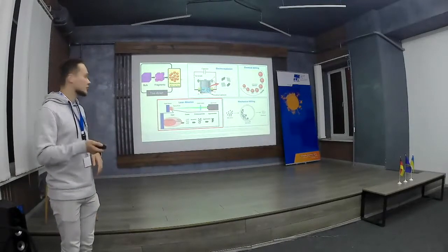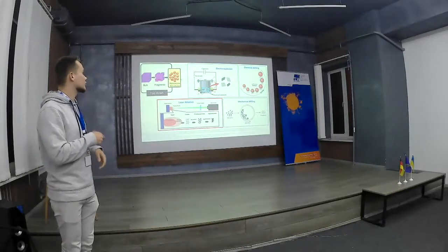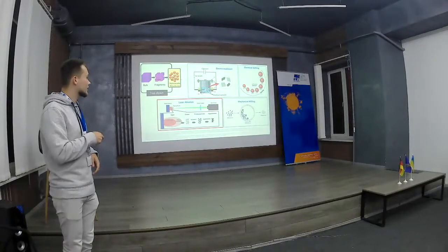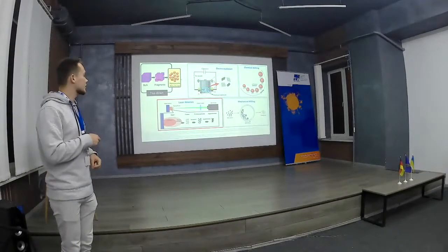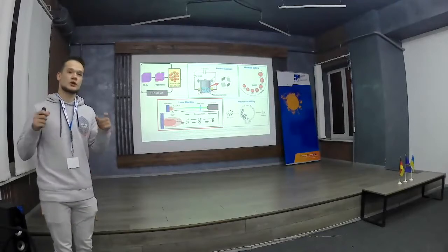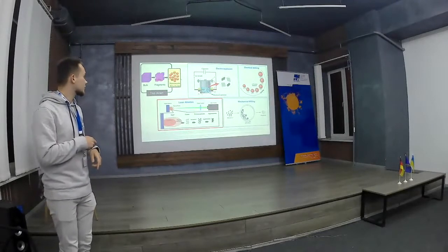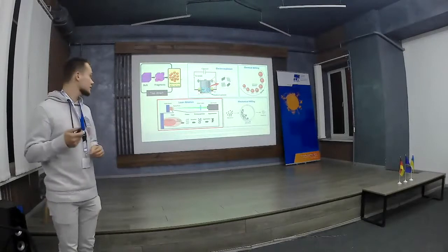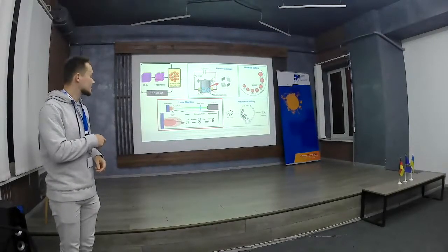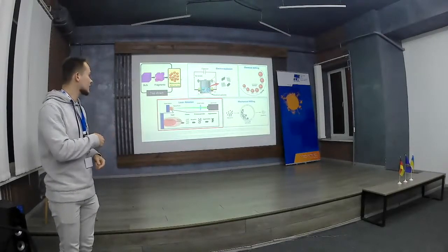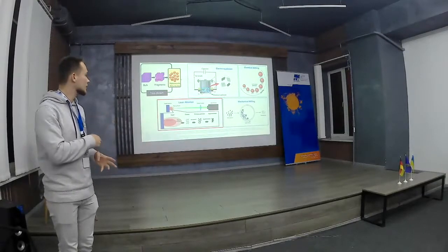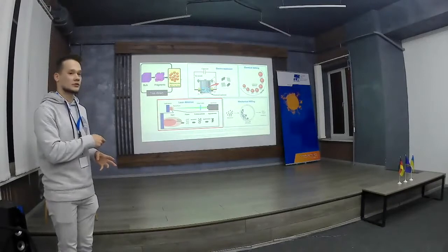Also there are other methods. For example, electroexplosion. In such a device we have a small metallic wire, and after the application of current, the wire heats up really fast, and this heating creates an electrical explosion. The products of such an explosion can create nanoparticles.